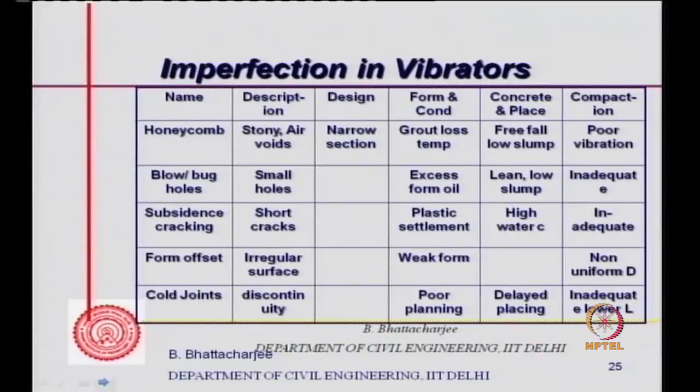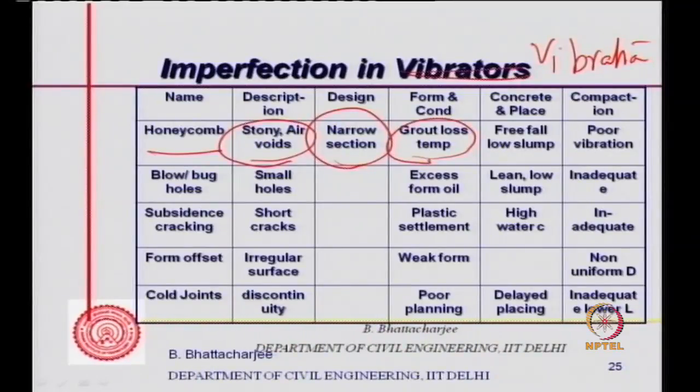Right. Now, imperfections due to poor vibration, essentially. Honeycombing, if you have not done the vibration properly, will have stony and air voids. It can generally happen in narrow sections, and grout loss can also cause this if the forms are not joined properly. Free fall and low slump concrete, and poor vibration can result in this.